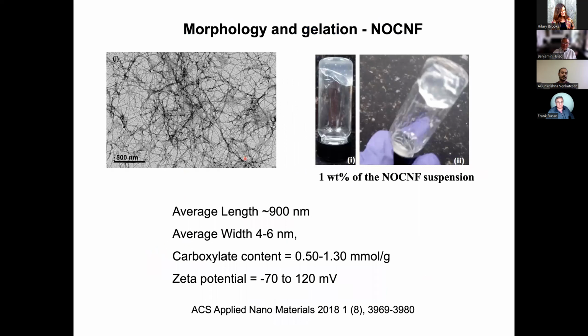We used our nitro-oxidation method, and we can extract very high levels of nitro-oxidized nanocellulose with a very, very high carboxylate content. The degree of carboxylate content depends on the chemistry.